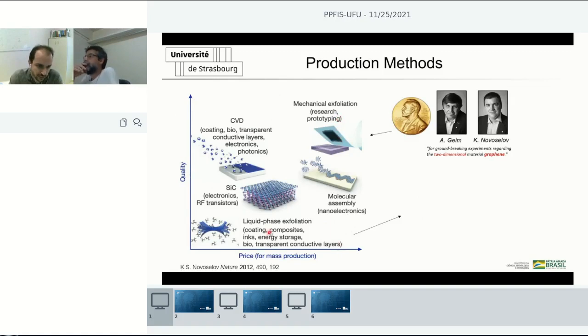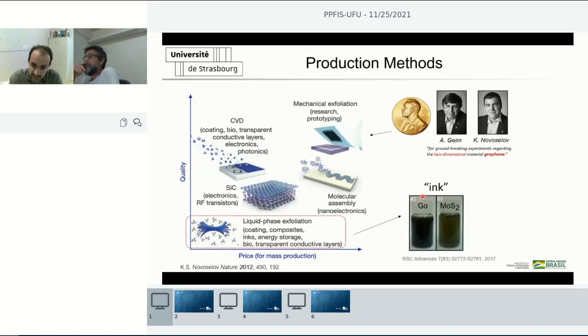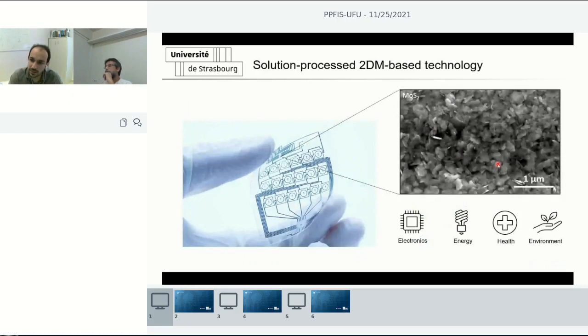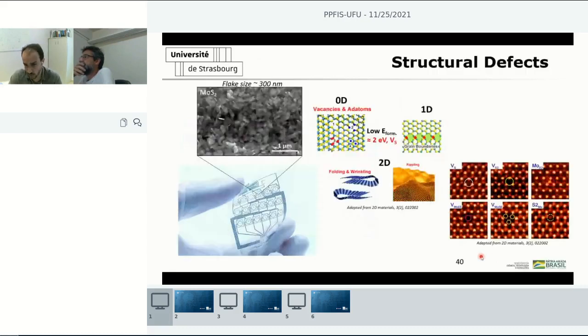There are several methods that I will not go into the details of, but I'd like to bring your attention to liquid phase exfoliation, which allows one to produce inks of 2D materials. Here we have a picture of graphene oxide ink and molybdenum sulfide ink. In this case, we exfoliate the flakes via intercalation of molecules in between them. This way you can produce 2D materials in large quantities. Here, for example, is a scanning electron microscopy image of a molybdenum disulfide film deposited on a given surface and produced via liquid phase exfoliation. This kind of film has large applicability in electronics, energy, health care, and environmental care, depending on the device that you make with this kind of material.